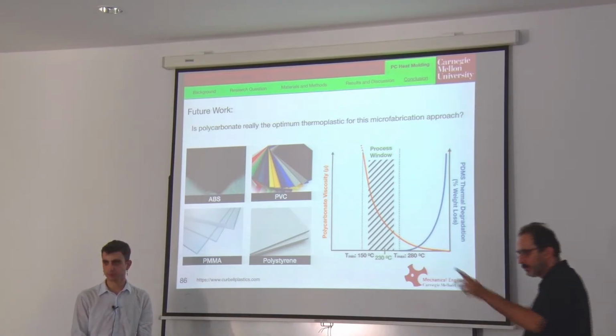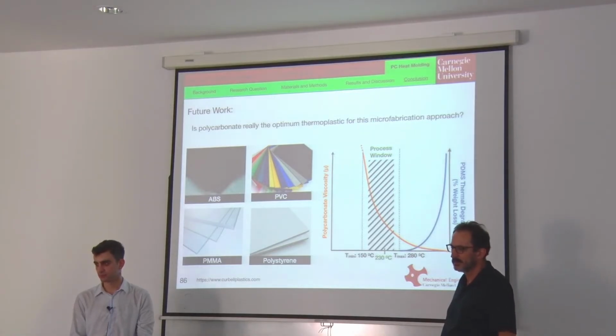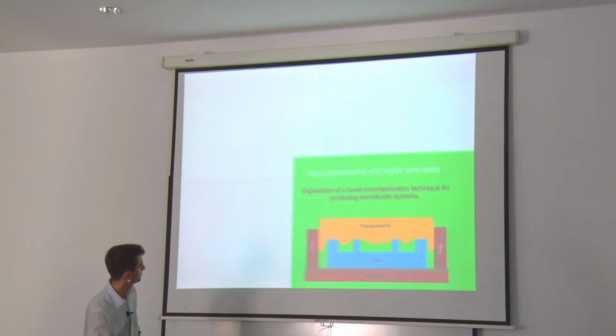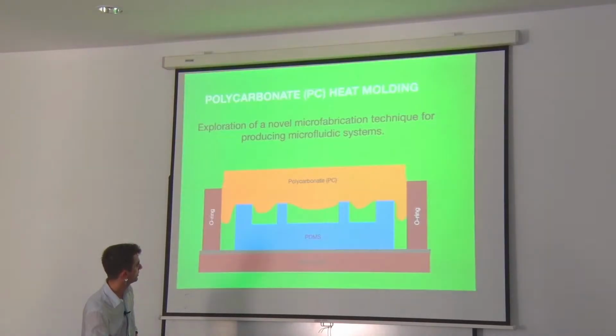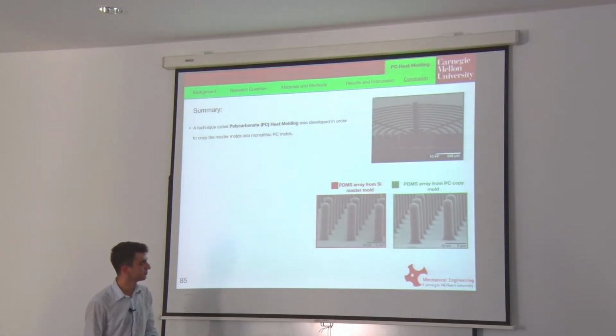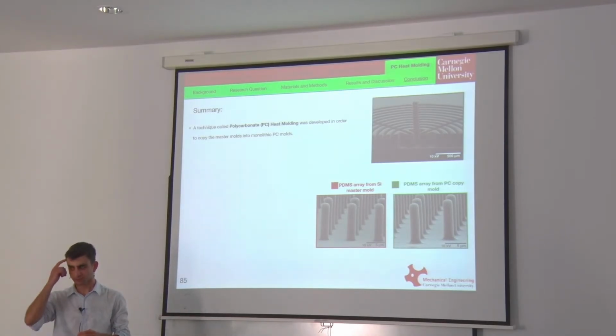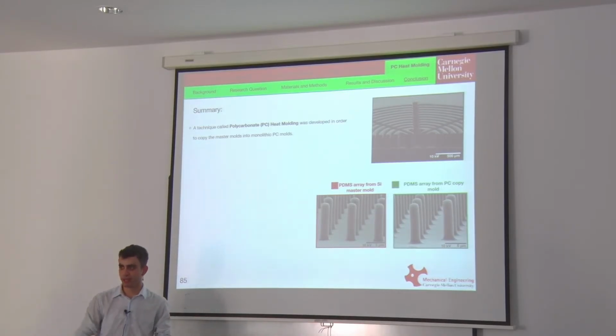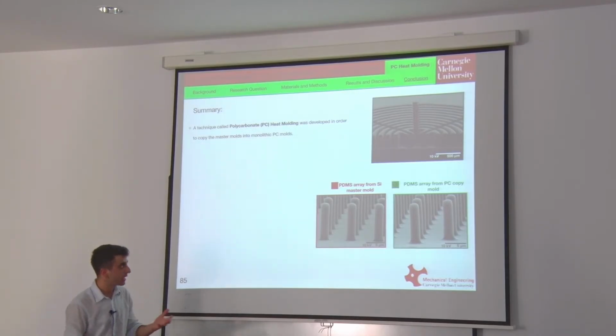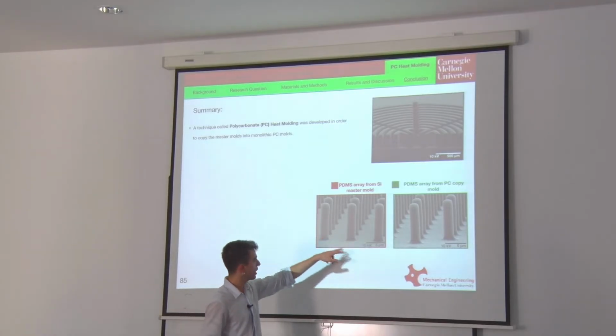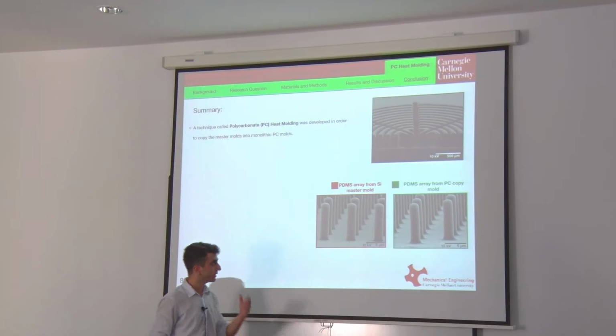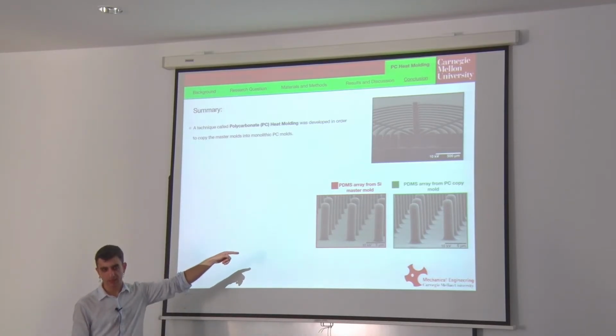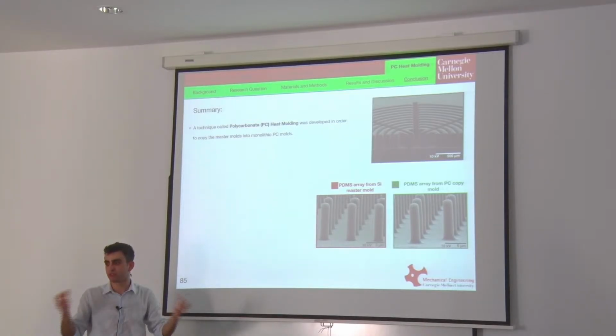Any other questions? You show that you remove those pillars of PDMS out of wafers or PC molds. They seem like the aspect ratio is about 4 or something like that. Exactly. Did you do any further surface processing for removing that PDMS? Because as far as I experienced, I would break most of them. Exactly, that's a huge concern. The question he asked is, how do you make these high aspect ratio features? Why don't they break when you are removing them from the mold? That's actually a huge concern, because if they break, they remain inside the mold and you cannot remove them. Although you don't break the mold, it renders the mold unusable.